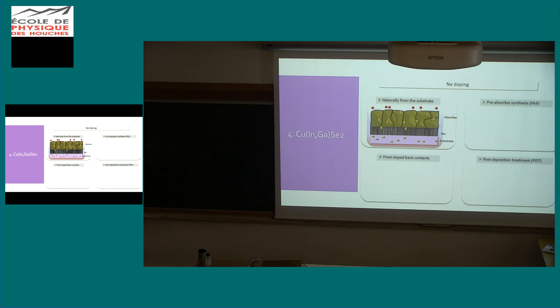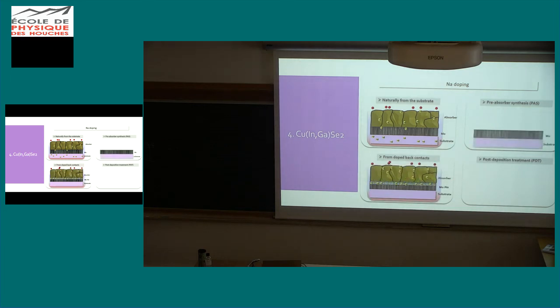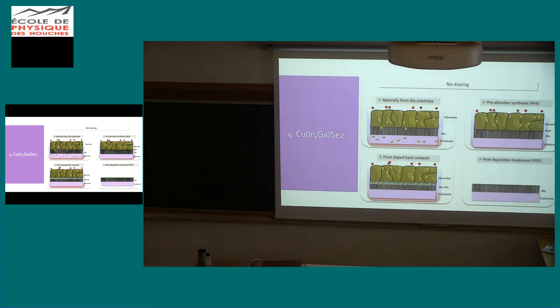Then using back contacts doped with sodium, like molybdenum doped with sodium, which will diffuse during the synthesis of the absorber. Or we can use the method called pre-absorber synthesis, depositing some sodium-containing layer on top of our back contact and diffusing it during the synthesis. And finally, we can first synthesize our absorber, then deposit some layer containing sodium and diffuse it in a further thermal treatment. These are the four methodologies, and all of them work very well.